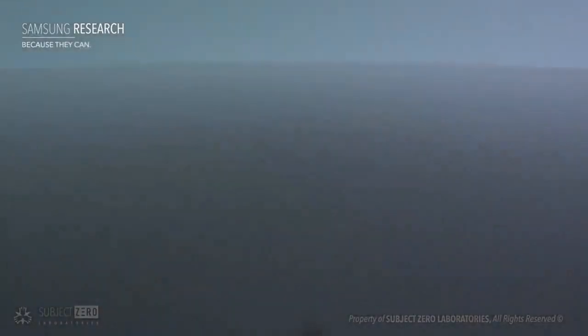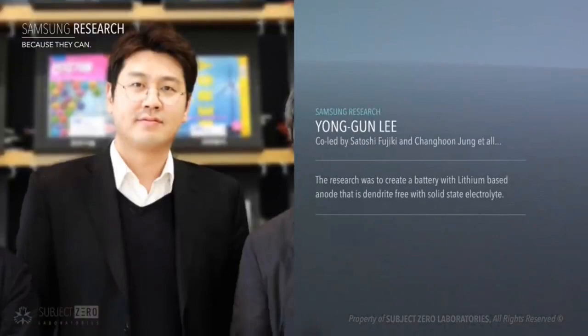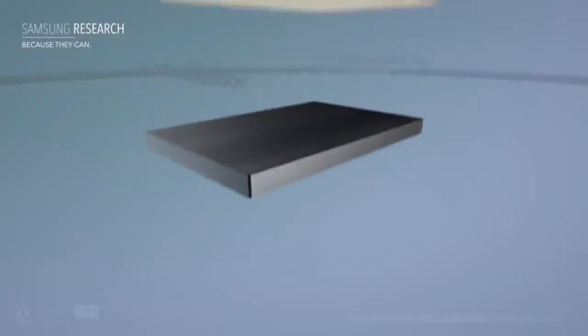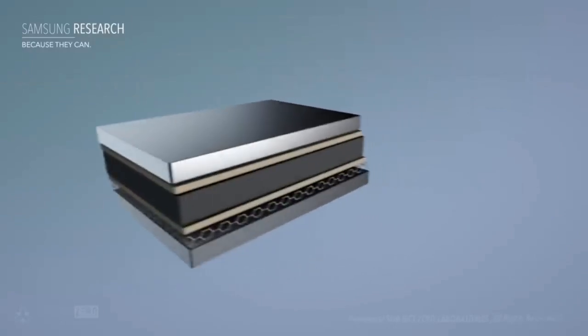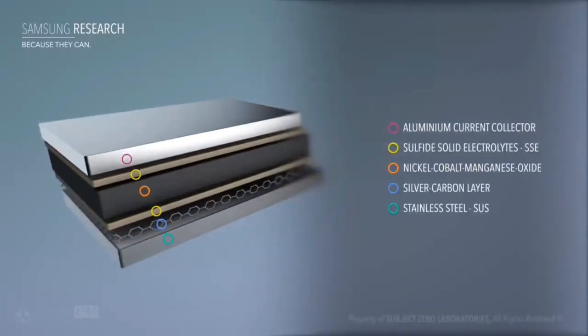Samsung research was led by Yong-Gun Lee for an all-solid-state battery. Their goal was to eliminate dendrite formation and increase coulombic efficiency. To do that, they sandwiched layers of lithium nickel cobalt manganese oxide mixed with a sulfide solid electrolyte on top of a nanocomposite layer of silver carbon. All of this is located in between a foil of aluminum and stainless steel as the current collectors.